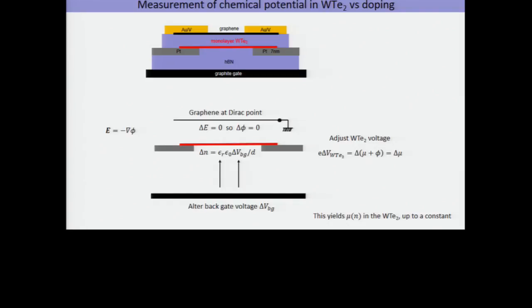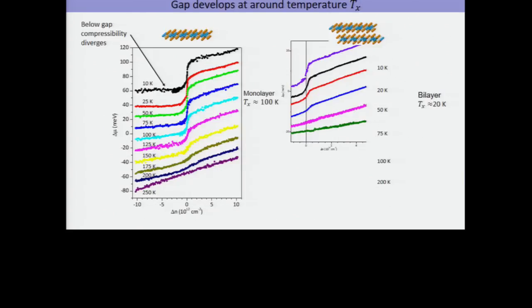So you directly measure chemical potential versus density, and it's very simple. We weren't the first to do the basic thing, but I think we got it to work very nicely in these devices. We use basically the same setup to measure the polarization of the bilayer, which affects the graphene above as well. I'm not sure, but this technique can be used for other materials, right? It's a beautiful thermodynamic technique. It's quasi-static, you don't need to oscillate, and you don't have a capacitance to measure. So even a poorly conducting thing, you can use this. So I think it's great.